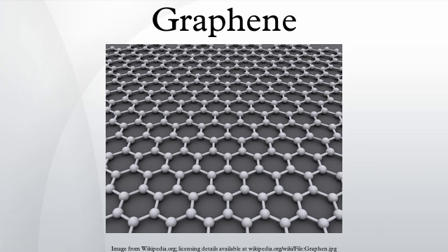Graphene's band gap can be tuned from 0 to 0.25 eV by applying voltage to a dual-gate bilayer graphene field effect transistor at room temperature. The optical response of graphene nanoribbons is tunable into the terahertz regime by an applied magnetic field. Graphene oxide systems exhibit electrochromic behavior, allowing tuning of both linear and ultrafast optical properties. A graphene-based Bragg grating has been fabricated and demonstrated its capability for excitation of surface electromagnetic waves in the periodic structure by using a 633 nm He-Ne laser as the light source.